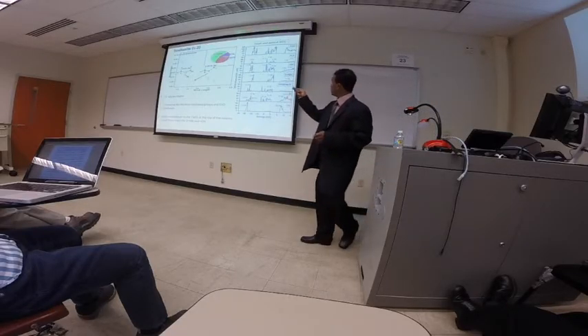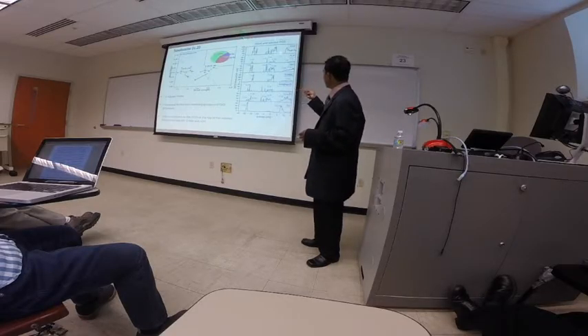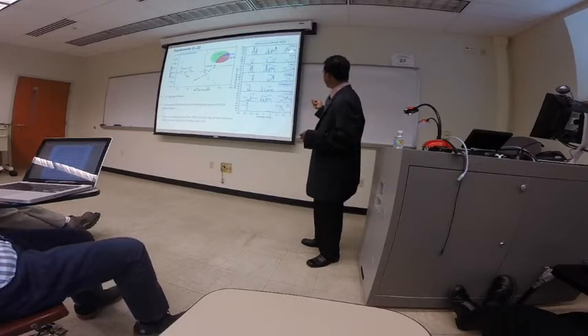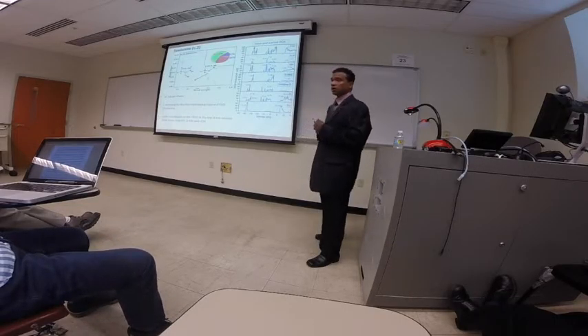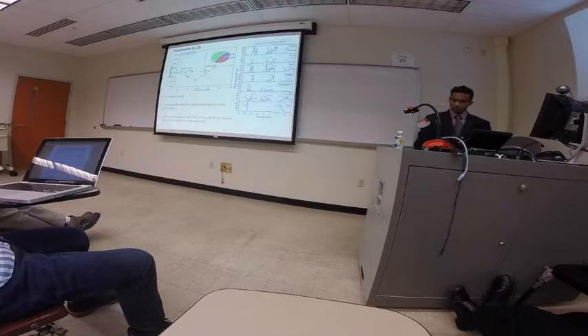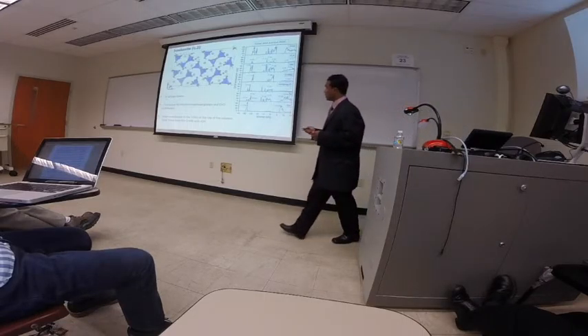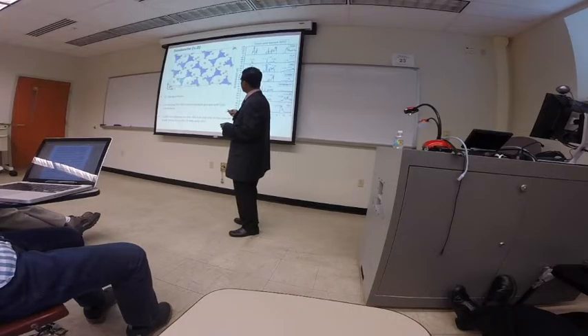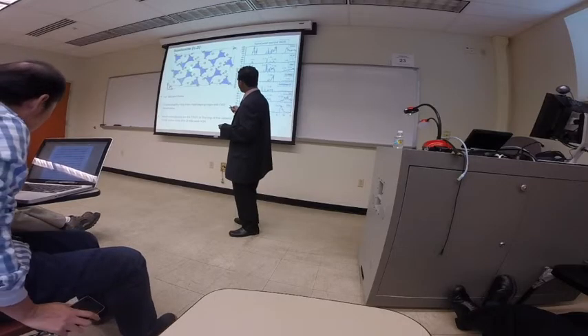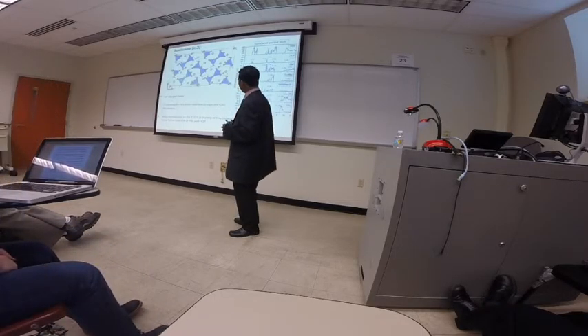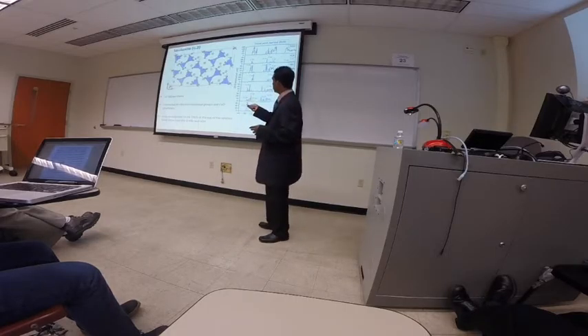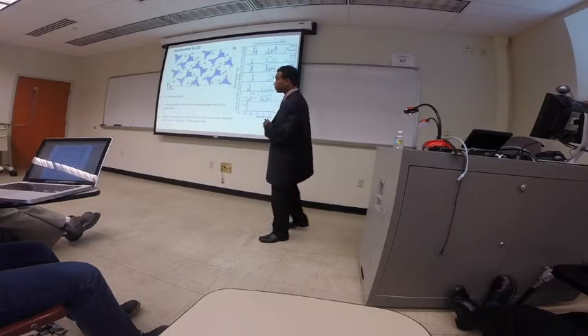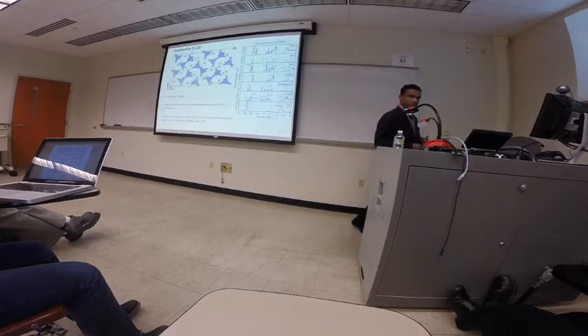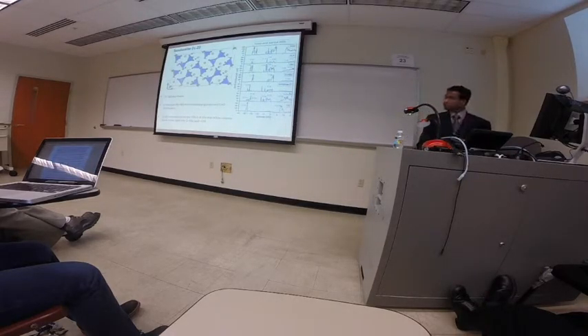And if you look at the total density of states, the main contribution to the valence band is from hydroxyl and hydrogen bonds, which gives rise to this unique property. So let's look at the crystal structure. It's arranged in a very peculiar way. You have silicate dimers arranged in a perpendicular fashion, and each silicate dimer has a hydroxyl and a water molecule connected via hydrogen bonds, and the entire network is based on these strong hydrogen bonding connections, which gives it higher mechanical properties. So these crystals should be further studied in future, hopefully.